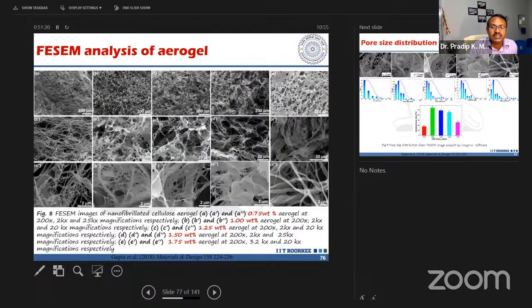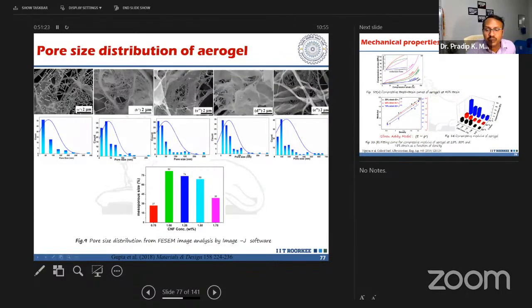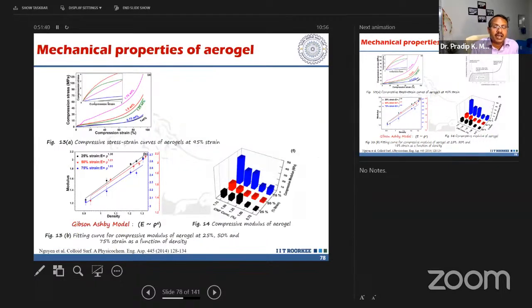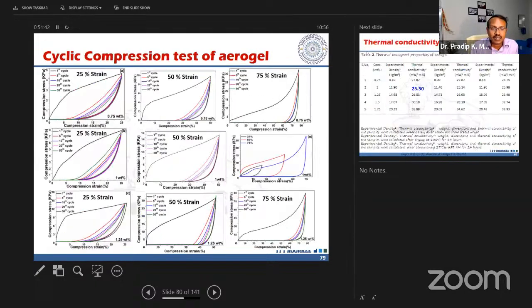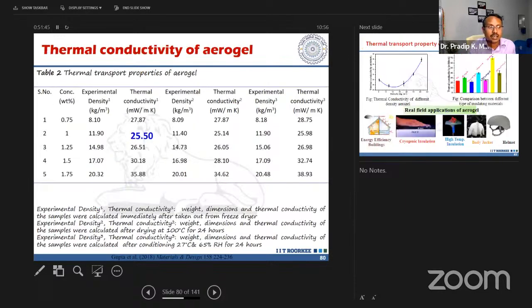And this is the BET analysis. I'm not going into details. What I want to tell you is that for 1 weight percent cellulose, 82% of the pores are in the mesoporous range, and mesoporous means 4 to 50 nanometer. A majority in the mesoporous range means thermal conductivity is supposed to be very, very less. Now I am comparing the thermal conductivity, then I will come back to the mechanical part. The thermal conductivity of air is 25 milliwatt per meter Kelvin, and if we are able to get just below air, then it will be super thermal insulation.